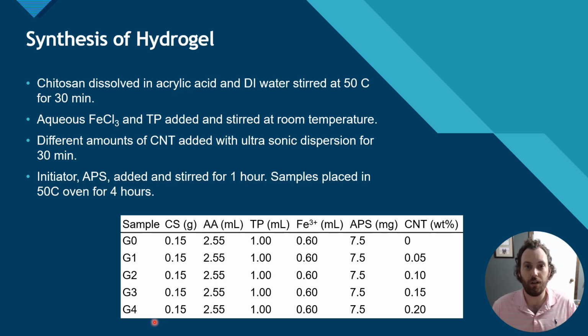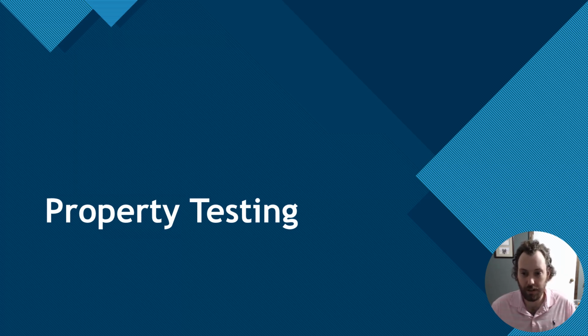For this particular research, we developed 5 different samples. What you'll notice is there is no modulation amongst any compound outside of the carbon nanotubes, with increasing weight percent from 0 to 0.20 weight percent. Now that we had synthesized our 5 compounds to be tested, we next needed to decide upon our physical testing to be done. The properties we would test, as I discussed briefly before, were adhesion, tensile, self-healing, conductivity, and sensitivity, which combined with conductivity will give us our stress sensing.